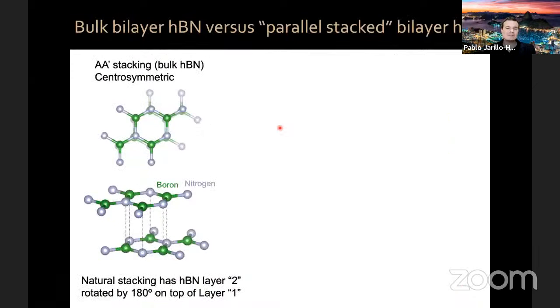Let me tell you about the special type of ferroelectricity we have found in parallel stack bilayer boron nitride. Now, hexagonal boron nitride is this material which consists of a honeycomb of boron and nitrogen atoms. It's like graphene, but with boron and nitrogen atoms in the A and B sublattices. Now, in the bulk, hexagonal boron nitride is centrosymmetric. If you have a boron atom in one layer, on top you have a nitrogen atom. You have AA' stacking, as is known.